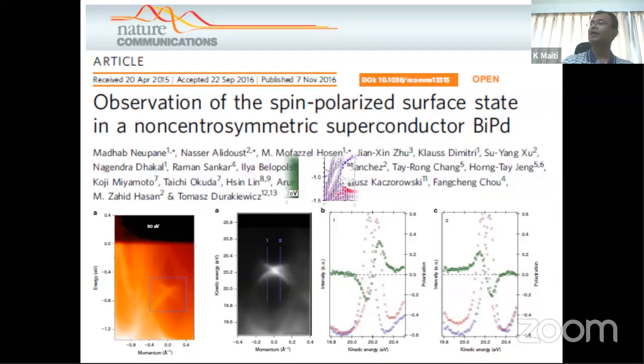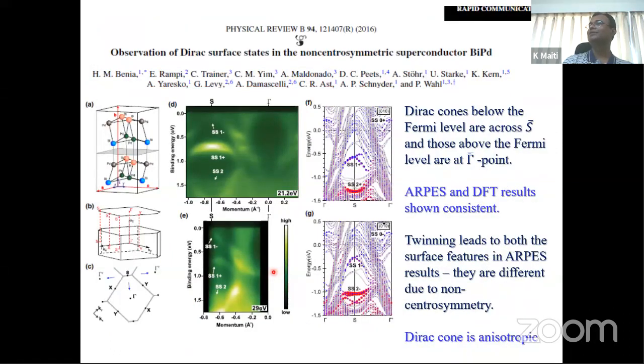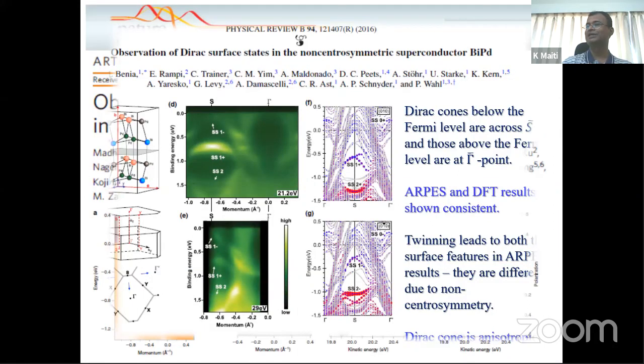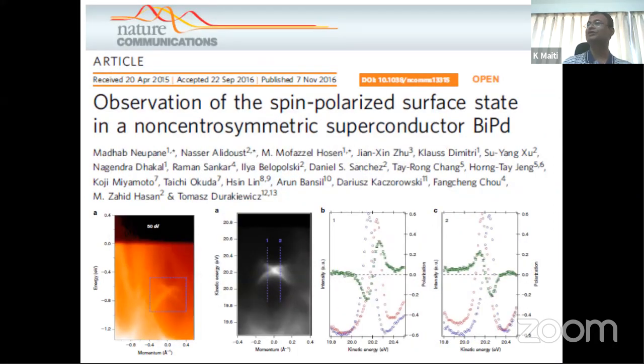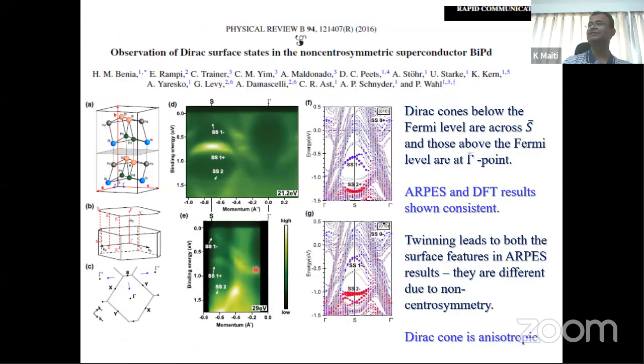Okay. Now there is another study by Andrea Damascelli's group. So they also looked at this. Now you can see that they also find the Dirac cone that has been shown here, in the previous one on an expanded scale. If you do it in this energy scale, it looks very close to each other, but actually they are the Dirac states, which is shown by calculation also. But what they see is that the Dirac node is appearing at a finite momentum, not really at the gamma point.